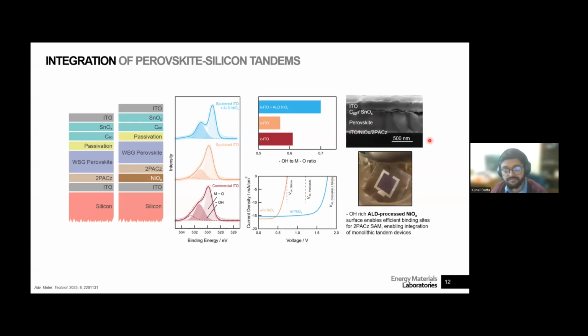And you can see the cross-sectional SEM of the tandem, and this is what the tandem looks like. It's a square centimeter device. So basically the integration at this interface is enabled by this nickel oxide layer, which is quite thin, but it's very, very important.